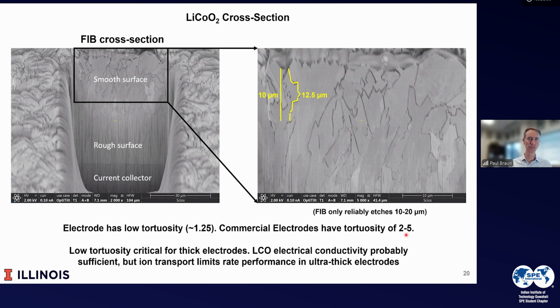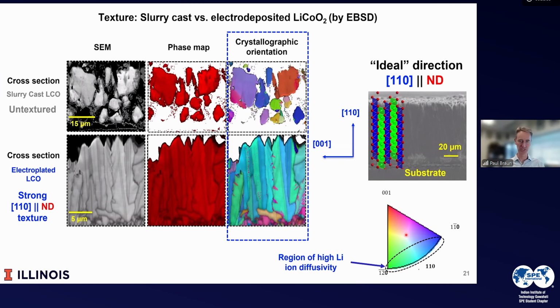So let's look a little bit more at the crystallographic structure of the material, because this is important not only for tortuosity, but for chemomechanics. In lithium cobalt oxide, and in fact in most cathode materials, as it charges and discharges, the material expands and contracts. If the grains are polycrystalline and randomly oriented, you will start to drive cracks in the material. On the other hand, if all the grains have almost the identical orientation, when I cycle it, it's all expanding and contracting the same way, and so there is very little in the way of crack damage or other defects in the structure.